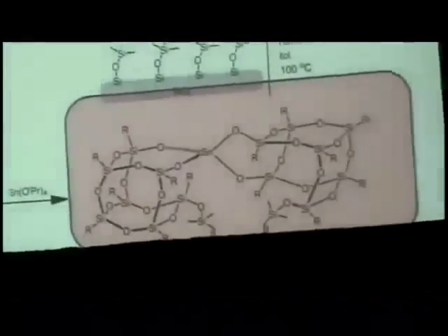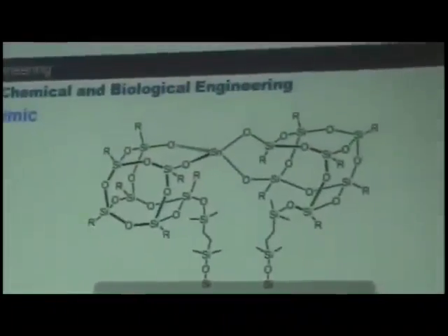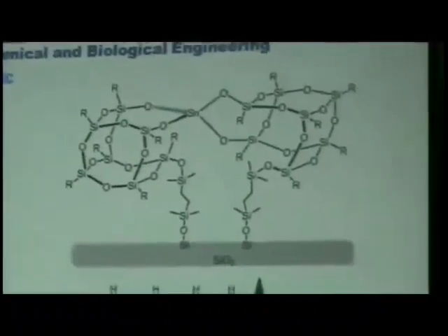So after we get this single molecule, we still have two silanols left, and we can use them to react with tetraisopropoxy tin, and hopefully, if everything works out right, we will be able to generate the tetrahedrally coordinated tin by reaction of two of these for one equivalent of the tin. Then, as I said, there is a double bond left behind, which we use to react with the silane. There's a functionalized silica surface by hydrosilylation, and we generate this material onto the surface.